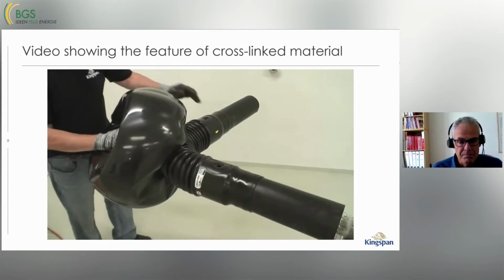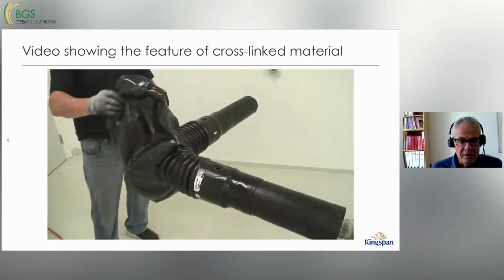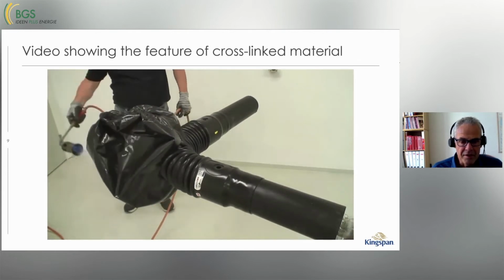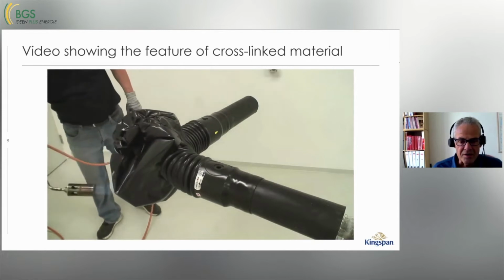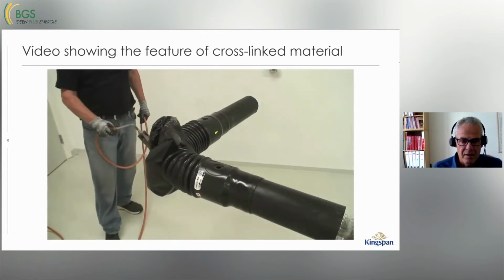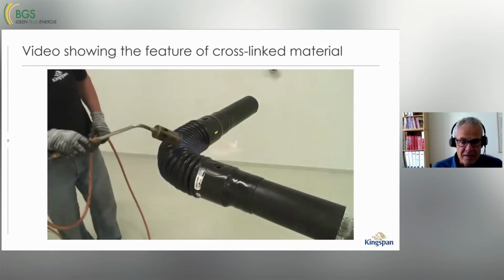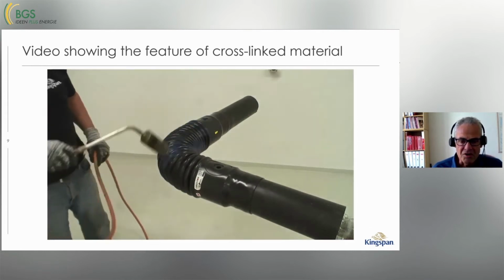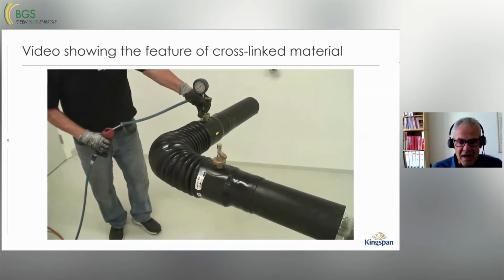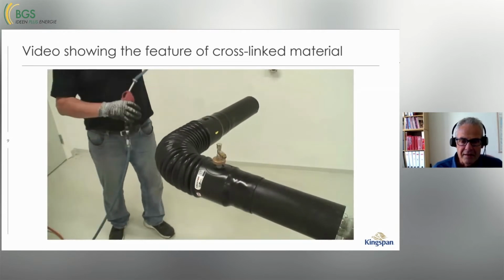Then we will cool it down. And when it's cooled down, we will start to heat it up again. And then the material will try to get back to the original shape. And that is what happens. After heating it for some time, it will get back to the original shape. And then, just to prove that it is tight and it's not broken, we will put pressure on again. And we can actually do this exercise again and again. So really, it shows the feature of the cross-linked joint being able to expand very much, and that it is not really sensitive to overheating. It will retain its shrink force and will not break the material.